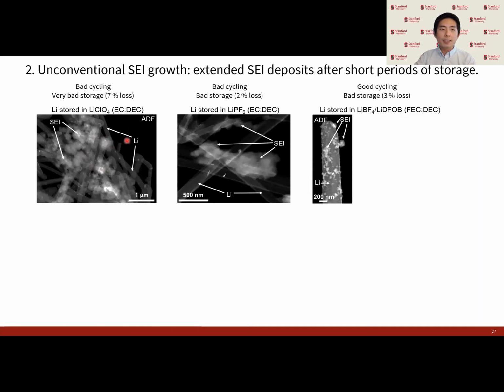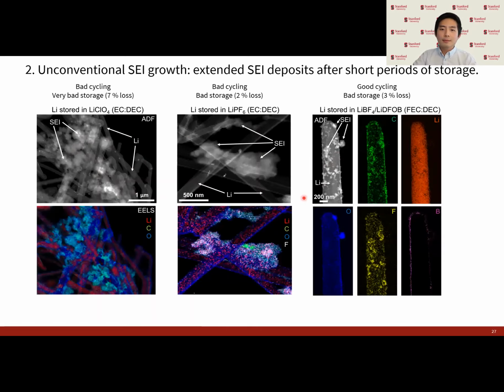In these dark field STEM images, the bright spots here are the heavier, larger SEI particles, and these light rods are the lithium metal filaments. And we can see these SEI particles exist both in these bad electrolytes along with this good electrolyte. Looking at the chemistry from EELS, we can see that there are differences in all of these different extended SEI growths in different electrolyte chemistries.